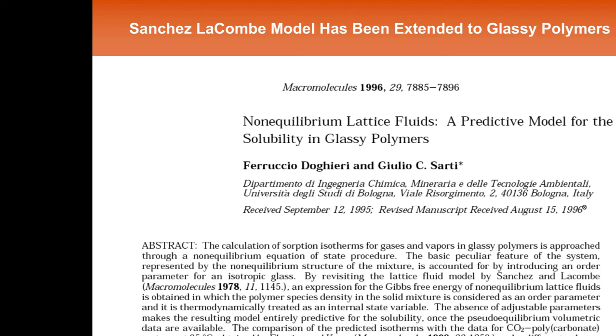So here again is the methane uptake as a function of pressure. Now we're at a fixed temperature, and this is pure methane. This is the methane sorption in the presence of just a tiny amount of butane, 0.05 atmospheres of butane in a mixture with methane in the gas phase. And this tiny amount of butane in the gas phase reduces the methane sorption.